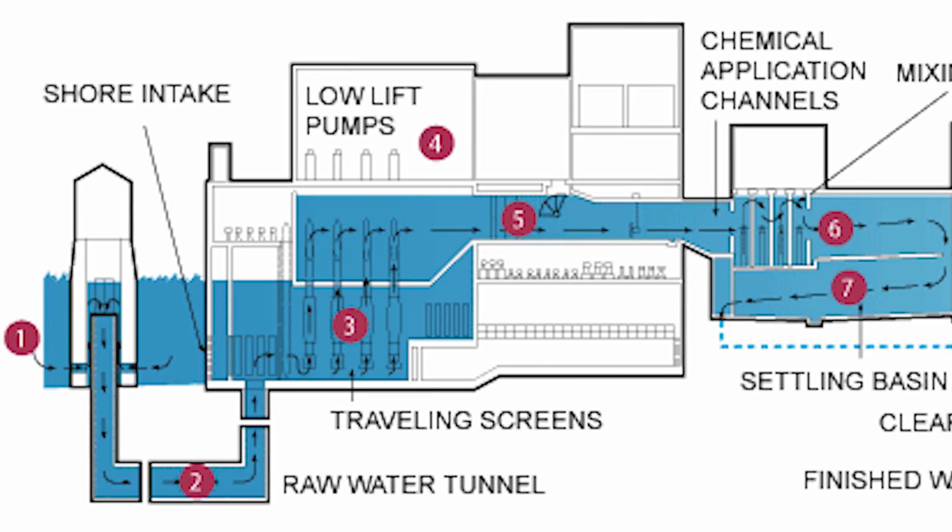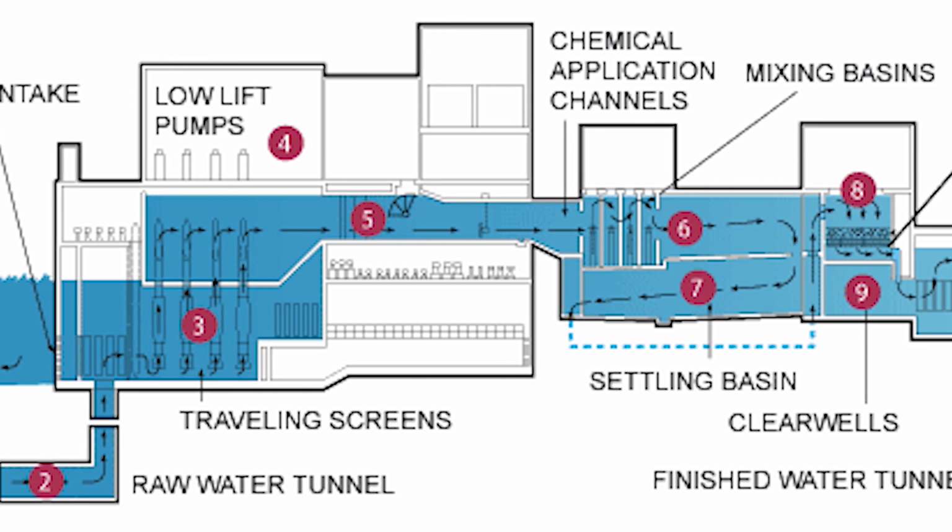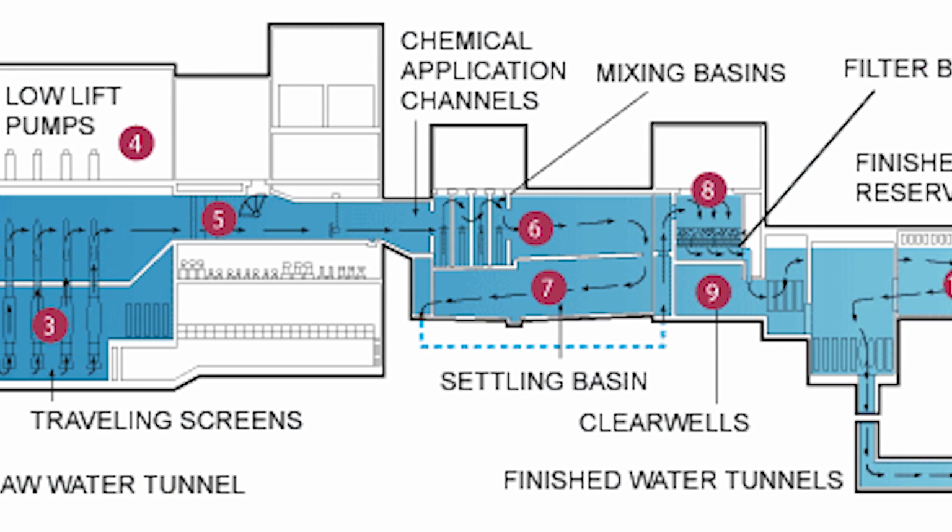So basically, they're adding these blended phosphates to our water at the water treatment plant, miles away from your property, hoping it coats all the lead pipes on the way to your property and your lead pipe too. Lead can leach into water from the lead pipe itself when corrosive water is running through it. That's exactly what happened in Flint, Michigan. Also, chemical reactions will occur from the water's acidity, the water's mineral content, the metal pipe itself that connects to the lead pipe to your property. That's what causes the lead to leach into the water.